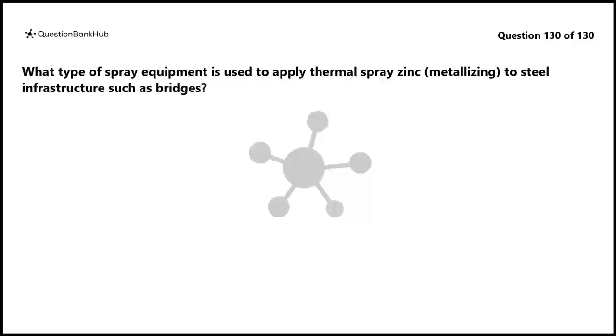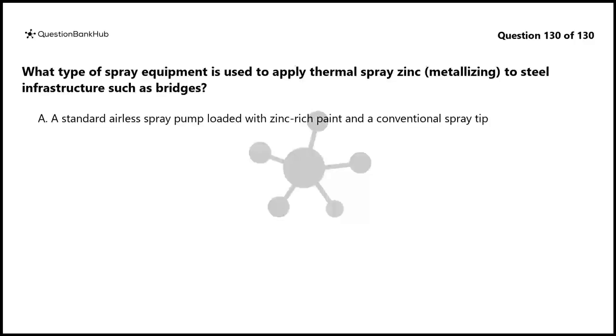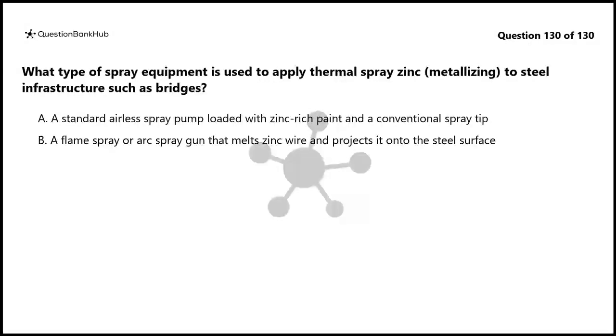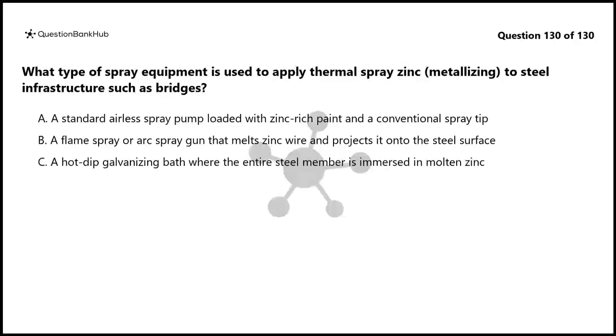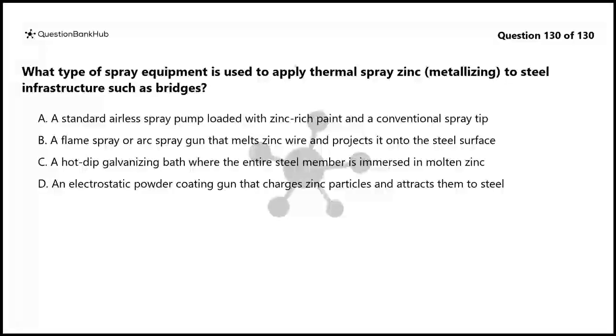Question 130. What type of spray equipment is used to apply thermal spray zinc, metallizing, to steel infrastructure such as bridges? A. A standard airless spray pump loaded with zinc-rich paint and a conventional spray tip. B. A flame spray or arc spray gun that melts zinc wire and projects it onto the steel surface. C. A hot-dip galvanizing bath where the entire steel member is immersed in molten zinc. D. An electrostatic powder coating gun that charges zinc particles and attracts them to steel.